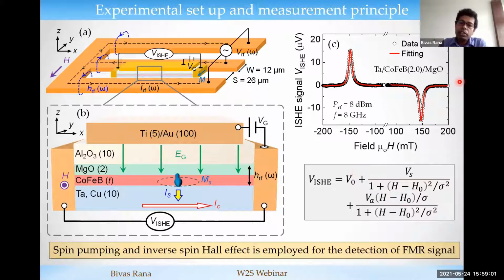So basically we measure the spin wave ferromagnetic resonance signal by the spin pumping inverse spin Hall effect technique, and this is the typical inverse spin Hall effect signal we observe. We fit it with a Lorentzian and anti-Lorentzian function to find out the resonance linewidth and the resonance field in the system.